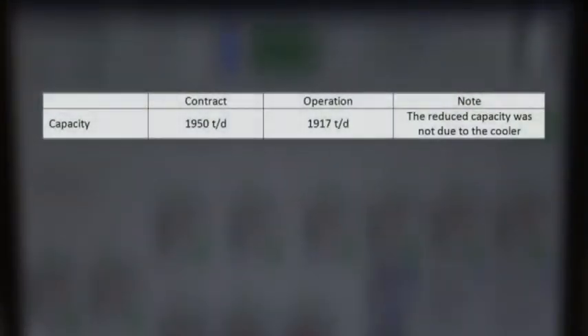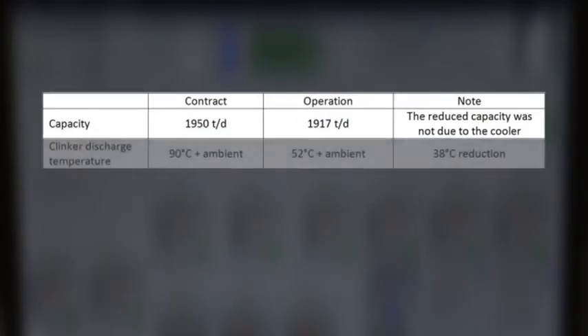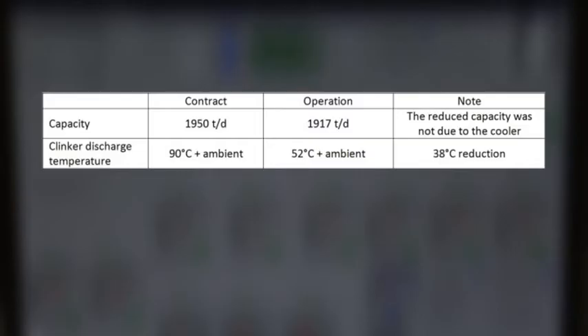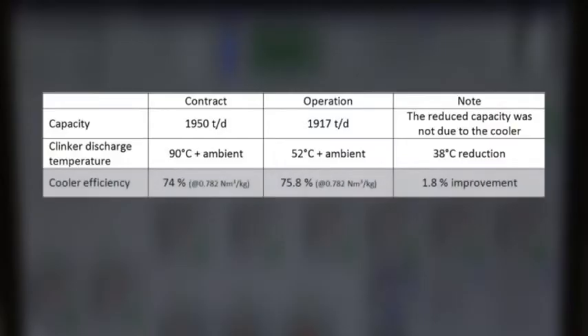During the operation tests, all guarantee values are clearly reached. The clinker discharge temperature is only 52 degrees Celsius above ambient. The cooler efficiency is 75.8%, well above the guaranteed value.